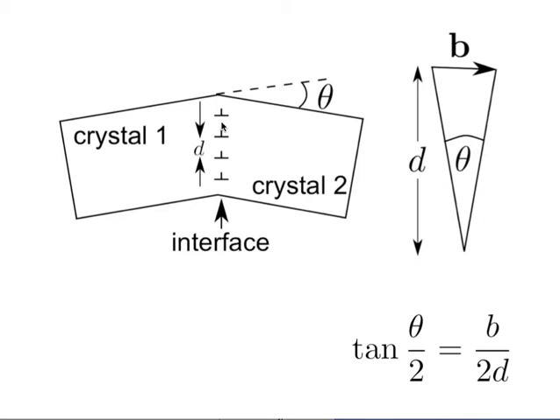So the effect of putting dislocations in arrays like this is to reduce the extent of the strain field approximately to the distance d. Okay, so the energy of the dislocation actually decreases, and you will get to a point where the angle theta is so large that the normal elasticity theory is no longer relevant because the cores of the dislocation start to overlap, right? So this model of the interface is only relevant when the dislocations are sufficiently far apart to be recognized as dislocations, right? If they get too close to each other, you're introducing a lot of disorder into the boundary, and it's basically an incoherent boundary. Okay?